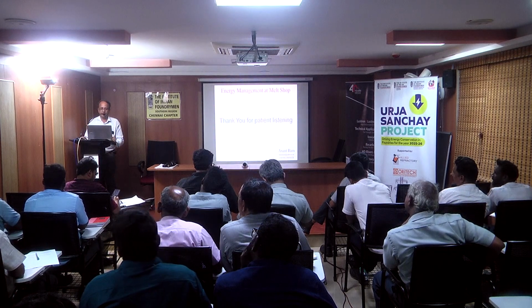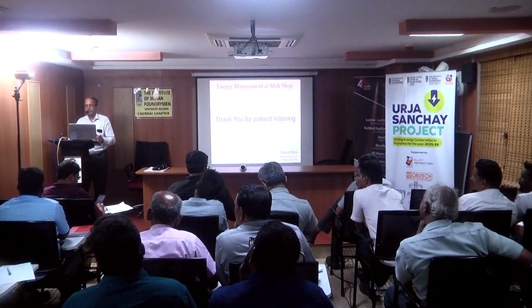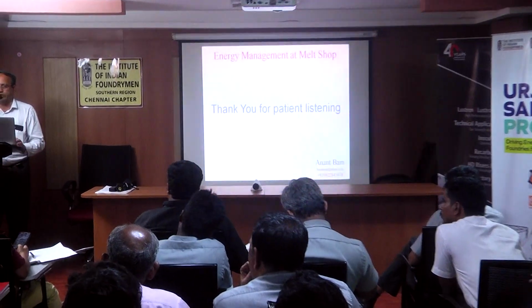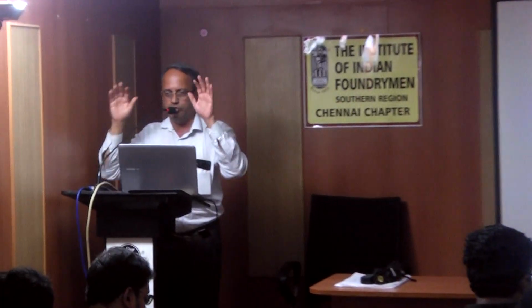Cover it. Cover it with Cerawool when it is not in charging mode. When you are not putting something in or not taking something out, it should be covered. That reduces radiation loss, and that is equivalent to nearly, at some cases where L by D ratio is good, the surface area is small. There it is equivalent to 20 units per ton of saving, where furnace is slightly broader. There it goes to 60 units. So that's a very easy location and spot where you can save much more units.